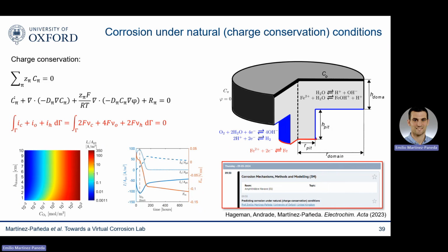And this is what you see here. So you basically can define this charge conservation condition here. And then we have tried to use these techniques, in collaboration with Carmen Andrade, to focus on understanding corrosion in reinforced concrete structures, to try to map the conditions, and understand questions related, for example, with the amount of oxygen that we need, how long a corrosion can be sustained in the absence of high oxygen, where anodic and cathodic reactions will happen. You don't need to prescribe that in the model. The model will give you that answer.